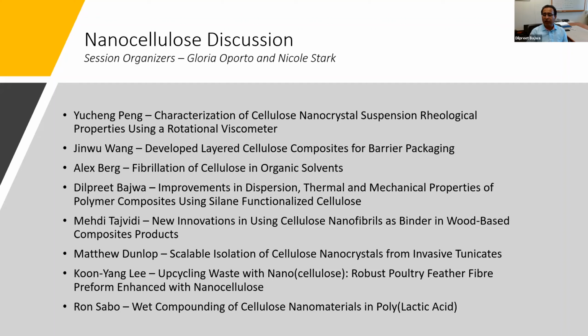We treated the CNC with silane, and we used a polyethylene matrix. We wanted to initially see what is the optimal silane treatment that would help improve dispersion. So we used polyethylene oxide of 1 million grams per mole molecular weight, and the silane 3-aminopropyl triethoxysilane. That was the silane treatment we gave, at different levels: 1-to-1 ratio, 1:2.5 and 1:5. PEO is water soluble, so we did not have a problem blending these solutions.